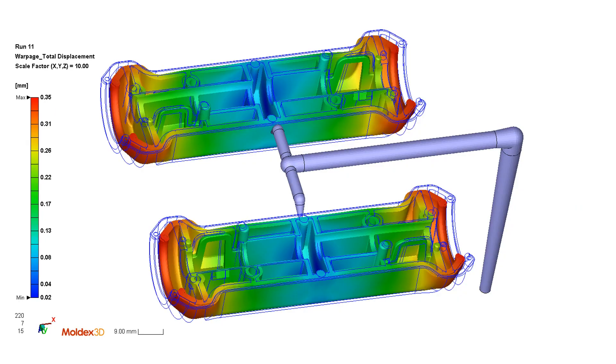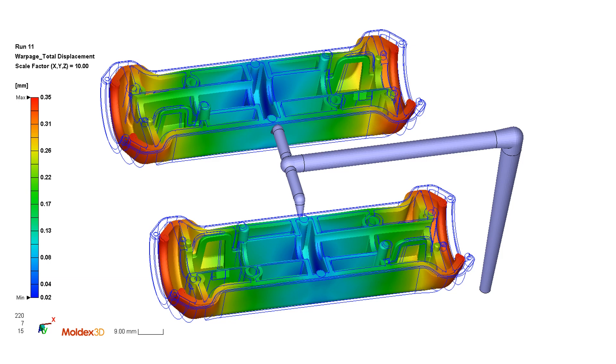Based on the molding conditions the fill processing the packing the cooling the system will calculate a linear shrinkage behavior. On screen we see the total displacement magnified ten times. In reality the part will shrink maximum 0.35 millimeters in certain areas. How can we depict this between the individual components? The individual components are X Y and Z deflection behaviors in millimeter.